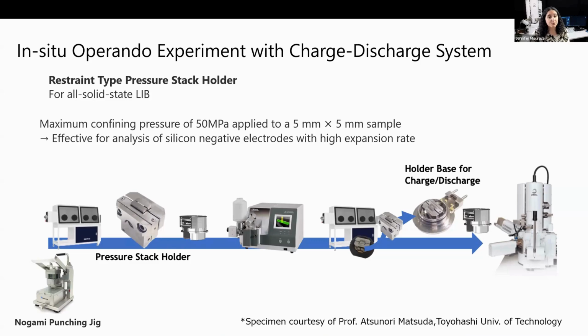So this holder allows preparation and observation while maintaining a confining pressure and is compatible with both our cross-section polisher and our air isolation workflow. Keeping the sample in the same pressure stack holder throughout the process ensures the sample integrity. In this experiment, NMC was used as the positive electrode, and there was a sulfide electrolyte. The sample was punched into a 5 mm square using the Nogami Punching Jig, transferred to the cooling cross-section polisher, and the cross-section was milled at -120 degrees.